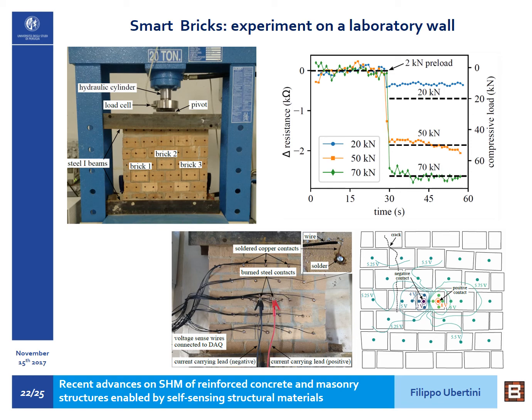It's important to notice that in this case, when we apply an electrical voltage across 2 electrodes of a brick, we are measuring not only the electrical properties of the single brick, but the electrical properties of the whole wall. In the experiments in the bottom part of this slide, you see the voltage measured in the different electrodes in the wall, so in different bricks, by applying a voltage in the 2 contacts of the brick placed in the middle, and you clearly see that the lines of equal voltage tend to go across the whole wall, which means that current flows not only in the smart brick but also in the neighboring brick.